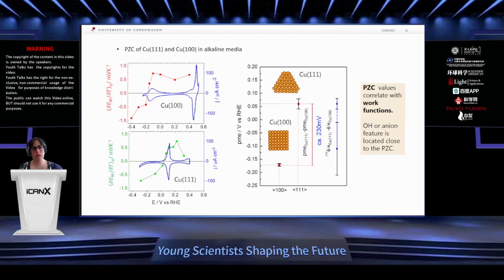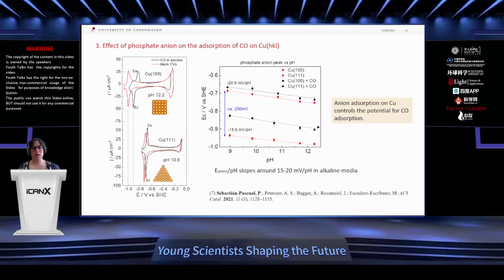structure. But in this case, we investigated the copper phosphate solution electrified interface, because with the phosphate buffer solution, we can investigate a wider pH range. So then we can also get information about how the pH is affecting the structure of the electrified interface. And after that, we also wanted to try to understand how the metal electrolyte interface structure can affect the adsorption of CO, of carbon monoxide on copper, because as I said before, carbon monoxide is a key intermediate in the